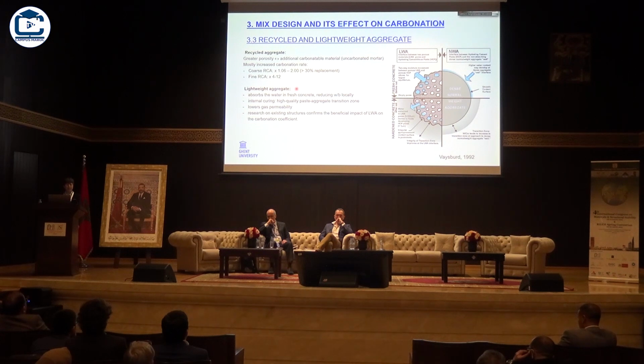On the other hand, apparently for lightweight aggregates, the internal curing effect is dominating. So in a fresh mix, these lightweight aggregates are absorbing water from the concrete mixture and then later slowly releasing it to provide internal curing to avoid self-desiccation, so that you get a really good quality interfacial transition zone, and that actually the gas transport is reduced rather than increased.